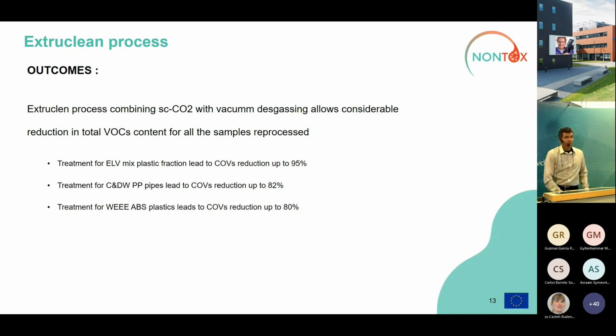For example, in the case of the end-of-life vehicles mixed plastic fraction, the VOC reduction was up to 95%. In the case of construction and demolition waste pipes, the reduction in total VOC content was up to 82%. And in the case of ABS from electric and electronic waste, the total VOC reduction reached up to 80%, allowing the obtaining of high quality recyclates to be used in high added value applications. So this is all from my side.